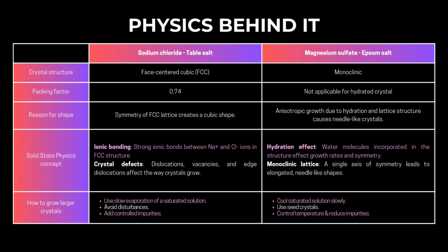The presence of the hydration in the crystals affects the lattice and creates an elongated structure. The asymmetric growth along different axes causes the magnesium sulfate to grow easily in one direction. As for the packing factor, 74% of the unit cell is filled with ions, while the remaining 26% is empty space. The high packing factor influences the strength and the hardness of the sodium chloride crystal, but at the same time, it is also brittle due to the ionic bonds. However, for magnesium sulfate, the packing factor is not calculated because of its hydrated nature.